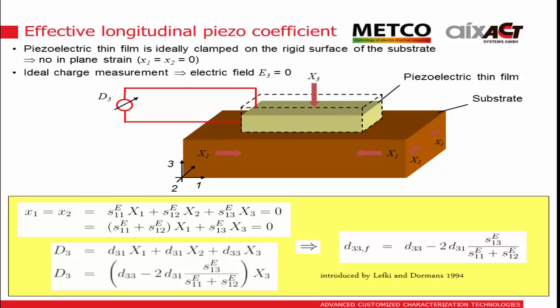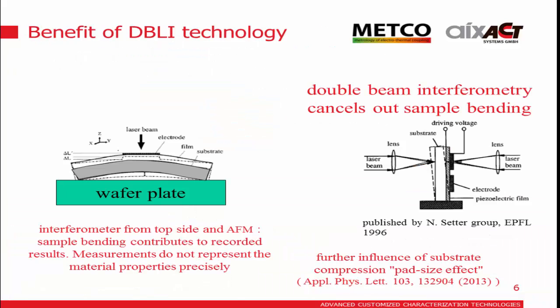This was introduced already in '94 by Lefki and Dormans. Additionally to this effective coefficient, the substrate creates a motion of our whole sample, giving us a typical bending motion of the whole substrate, which is easily orders of magnitude higher than the actual elongation of the film itself.